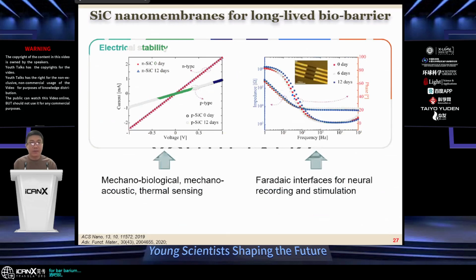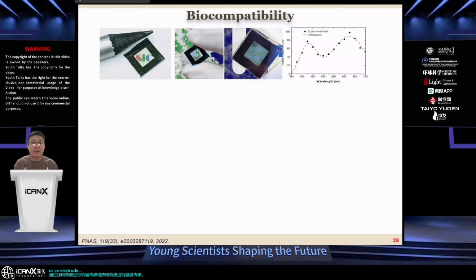And we also measure the electrical property stability of silicon carbide in PBS at 96 degrees C. The conductivity of both N-type and P-type remain constant, and its electrochemical impedance spectra are also quite stable after 12 days. So it means you can use that as a sensing element, either through the piezoelectric effect for mechanical sensing, or thermoelectric effect for temperature sensing, or as an electrode for stimulation and recording.